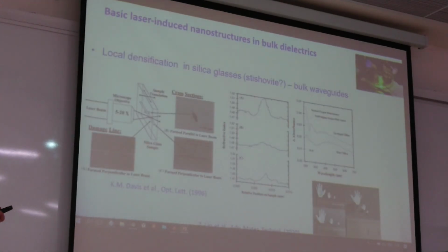Okay. And the last part of my talk, I have maybe 5 more minutes. We will talk about nanostructure in bulk dielectrics, which is again related to defects, but now with some functional structures. Initially, the low energy inscription in bulk dielectrics by femtosecond lasers corresponds to local densification in silica glasses. And this enables writing bulk waveguides, so people can scan the silica glass and write a waveguide.